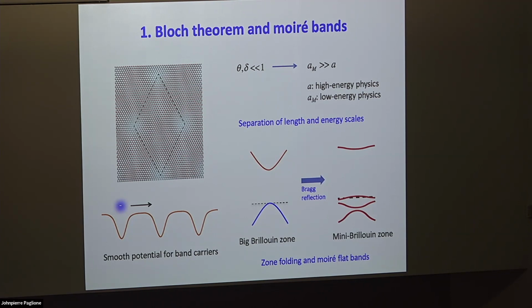Yeah, actually the tunneling you can control very well. The tunneling is a resonant process. If you have bands from one layer and bands from the other layer, and the two bands are close in energy, then the tunneling is resonantly enhanced. But if they're far apart, they are not resonantly enhanced. So by changing the distance between the bands in the two layers, which you can do by applying a vertical electric field, you can change the Moiré potential trapping depth. You cannot change the contribution due to the lattice reconstruction, but you can change the tunneling part quite well with the electric field. So that's a very nice way to tune the trapping potential depth or the band structure of the material.